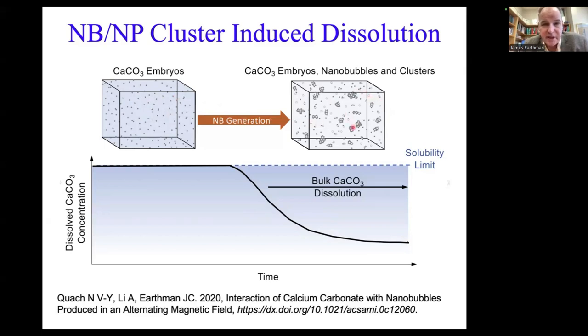Those clusters are going to stabilize these embryos over here, and they're going to keep them from dissolving back in solution. And you're going to force the concentration below the solubility limit. If you keep adding more and more nanobubbles to this, the concentration won't be able to catch up. You can keep it down, and you can keep dissolving the fouling solid that you got in the system by just adding more and more nanobubbles this way.